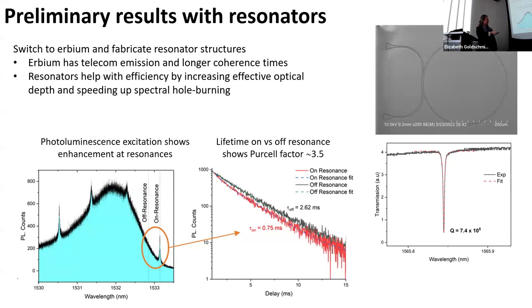And if we measure the lifetime of that emission on a resonance and off a resonance, we see about a factor of 3.5 in terms of that lifetime speed up. So what that is, is a Purcell enhancement. Right, and so the coupling of the atom to the resonator structure is faster than the coupling of the atom to free space, and so it emits faster into the resonator than it emits just into the waveguide. And I think this resonator actually was only like 1 × 10^5, and we also think maybe we can start to make slightly smaller resonators, and that Purcell enhancement should go like the quality factor divided by the cavity volume. So we think we can up that Purcell factor a little bit.